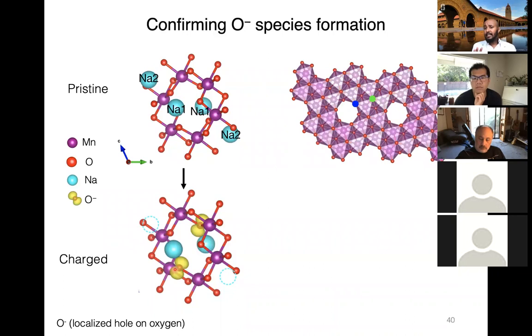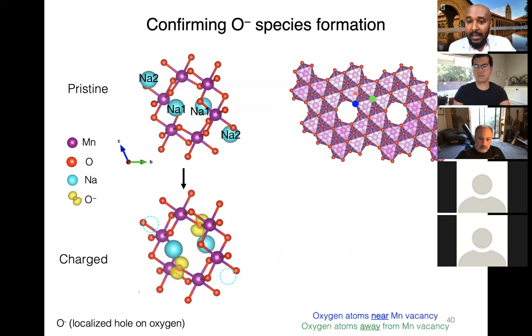And like I mentioned, this system has a very ordered defect. And this is very relevant because the oxygen atoms near the vacant site, shown in blue, have a different local environment, different electronic structure compared to the oxygen atoms away from the vacant site. And such difference plays a role in terms of stabilizing this localized hole or O- species.